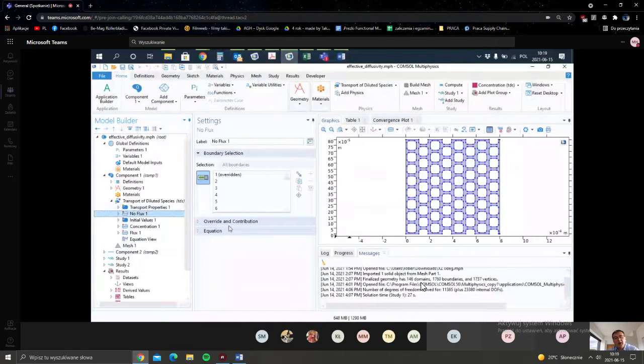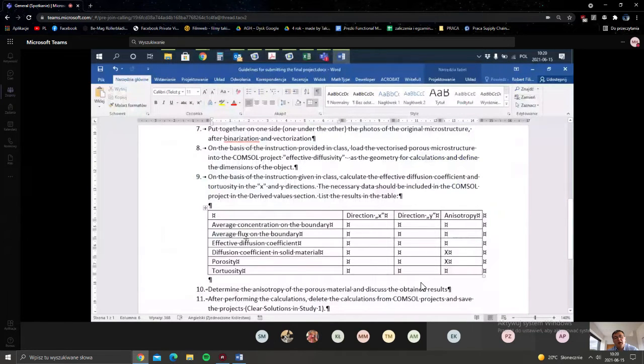And you will recalculate those average concentration, average flux, porosity of course will be the same, and based on that you will calculate effective diffusion coefficient and tortuosity. And if you have those values for the direction X and direction Y, you can calculate anisotropy by dividing the value in direction X by the value in direction Y. And if this coefficient is different than 1, it means that it is anisotropy. But what is the value? It can be small anisotropy, bigger or very high. So it depends on this value here in this column.